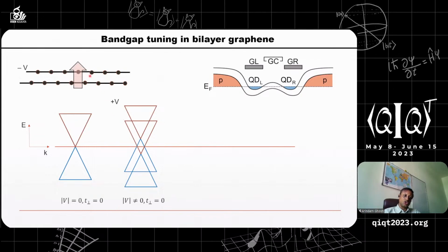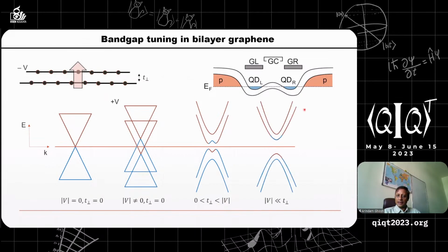But now I switch on an interaction between the two layers, because they're so close to each other, the electronic bands overlap. As a result, there is a coupling between the upper and the lower layer. And the moment you switch that on, you will see that a band gap opens up in the electronic structure. And if you make the coupling very strong, then you get parabolic bands, which is tunable by the electric field that you apply. Which is very nice, because from the same platform of bilayer graphene, in certain regions you apply an electric field that opens up this band gap, and that creates these quantum dots.